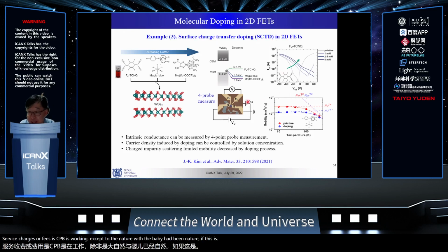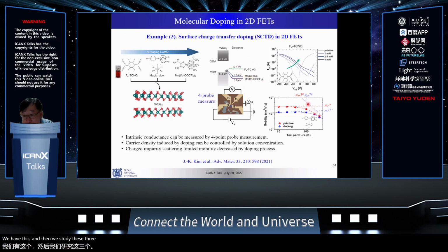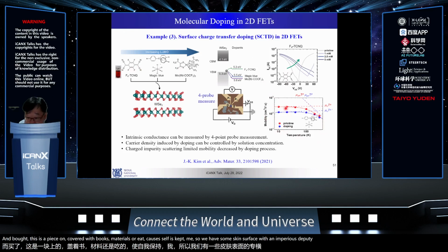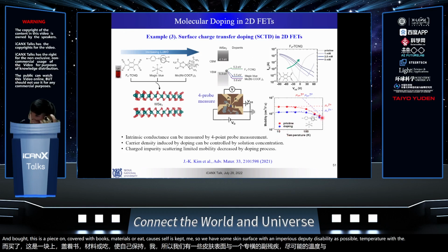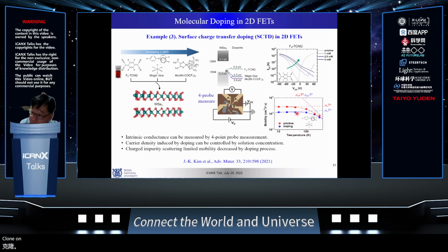And then we studied these three molecules, and the current increased with more doping. But this is a dopant layer on top of the surface of the material, so it causes surface scattering, impurity scattering. This is mobility as a function of temperature down to 10 Kelvin, showing phonon and impurity properties. This one is pristine, undoped. This one is surface doped, and the mobility decreased because of the surface scattering.